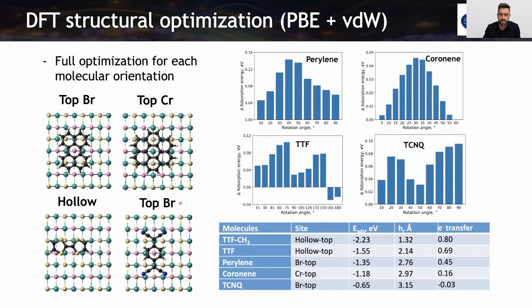This is after the full optimization. We were also testing the orientation, as I said before, and here we can observe the adsorption energies according to this evolution. Now, in this case, the perylene, coronene, and TCNQ are in this position that we have here, but in the case of the TTF, we need to rotate around 165 degrees. This is the minimum energy, because in the TTF the sulfur atom is pointing towards a bromide. We have here the adsorption energy, so it's clear that the TTF, and once we know that, we also add a methyl group to make it more donor and to have more adsorption energy.